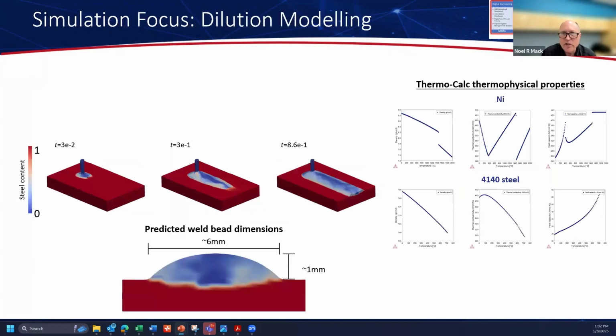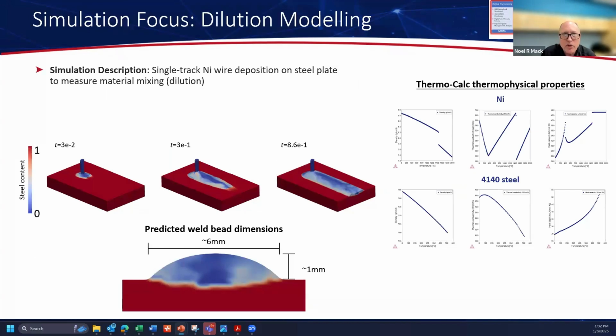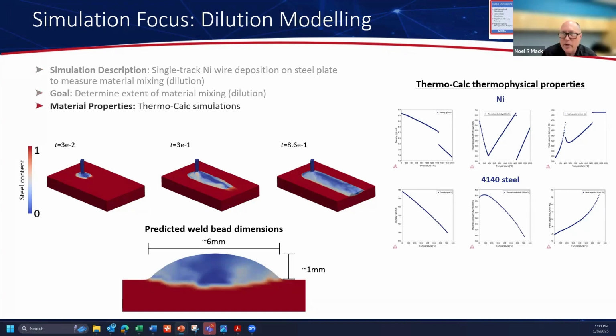So in this case, our simulation focus is really on dilution modeling. Unfortunately, again, most of what we're looking at are not very exciting parts. We start typically with a single track. In this case, it was nickel deposited on a steel plate, looking at measuring things like dilution. The objective here was to determine the extent of the material mixing and the dilution. And in this case, we use Thermo-Calc, and then on the CFD side, using Flow-3D as the CFD code. Here at the bottom graphics, you can see the weld beads as they are simulated, as well as some of the thermophysical properties on the right-hand side.